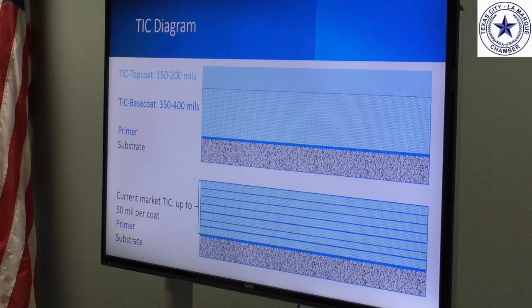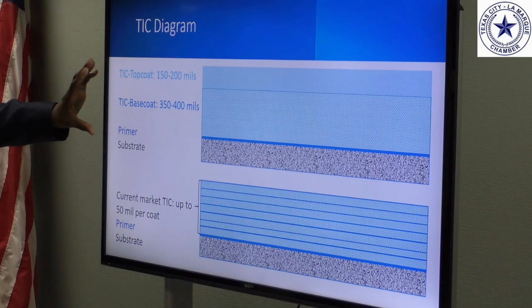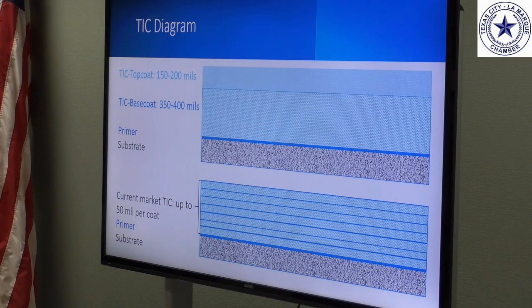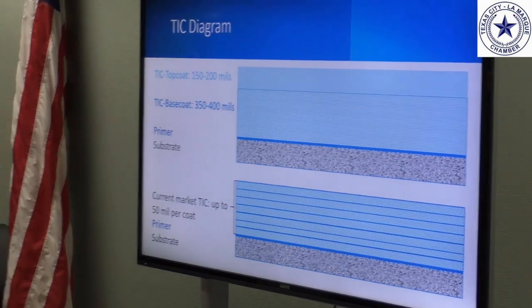Now, I say that, but I also say that you don't necessarily have to apply this film thickness. It depends on the temperature you're operating at. You can go lower, you can go higher. It depends on what you're operating at and what you want to have for thermal efficiency. So we do a very complicated calculation to determine what film thickness gives you the thermal efficiency you're looking for. It's called NAMR software. And we have some industry experts on our team who are very versed in doing this. A guy by the name of Neil Wiles.